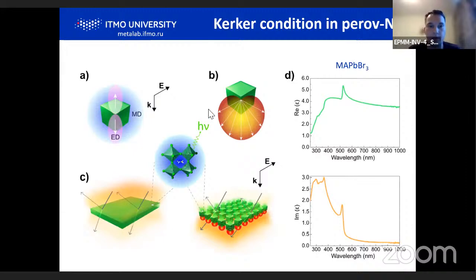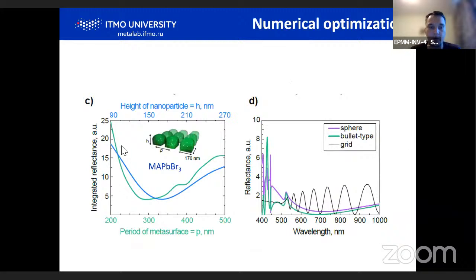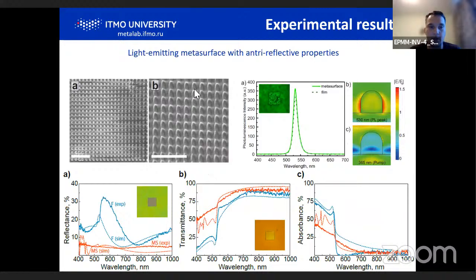One of the effects in all-dielectric nanophotonics occurs if we combine electric and magnetic resonances at one frequency and then look at what is going on with the incident light. There is the so-called Kerker condition, where we can suppress reflection from a layer of such nanoparticles made of perovskites. We first provided numerical calculations for an array of such nanoparticles made of perovskites, and we observe that there is a minimum in integral reflectance for such metasurfaces. Then we fabricated metasurfaces made of this material.